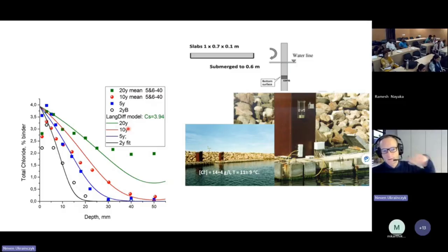And then we did even one more round. We told them, okay, now these are the results, because this is what you also have in a structure. You need to predict, but then you can also, after 20 years, you can also see. When you do the maintenance, you can take the profile, go to the site, measure the chlorides in the concrete, and then you have the profile after 20 years, and then you can also correct your model. So we did the same exercise. So these are the measurement points, and those are the predicted by model.